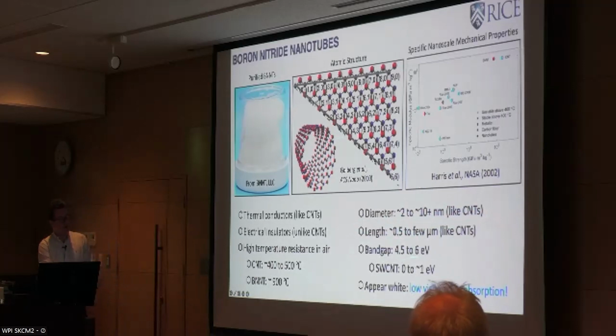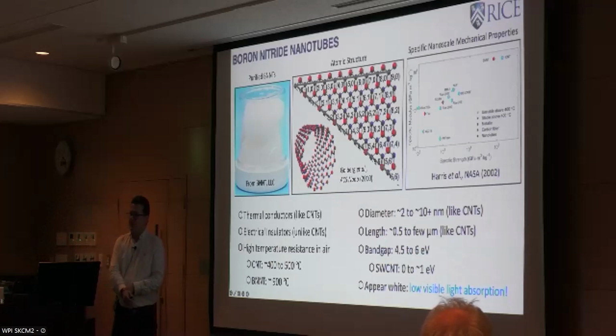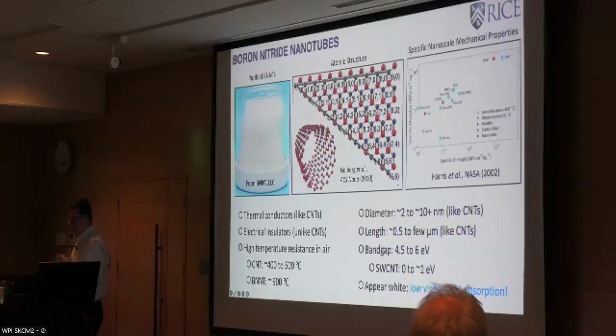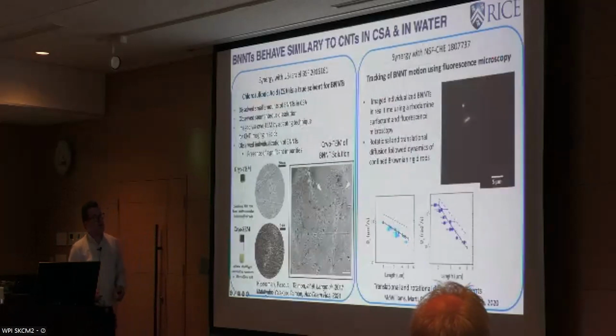The big difference is band gap. The band gap definitely puts it into the insulating region, and also gives this a white appearance, which also means that there's low visible light absorption. And I showed you an image of liquid crystals of nanotubes. It was done on very, very thin samples. When Ivan and I tried about 10 years ago to do anything a little more sophisticated than just optical imaging, we couldn't because the material absorbs. But this material is not going to absorb light as much.